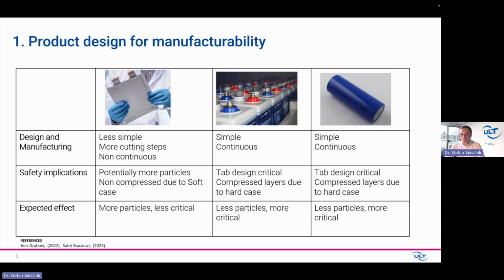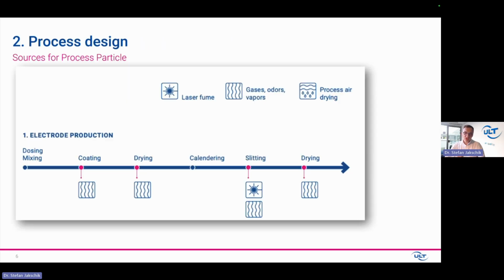The other two, the prismatic and the cylindrical cell, are very stiff. They cannot move. All the material is pressed in. So here particles are much more critical. The good news is, since the production is less complex than a pouch cell, there are also fewer particles available there. Especially for the cylindrical cell, which probably has the best process control in that kind of production.